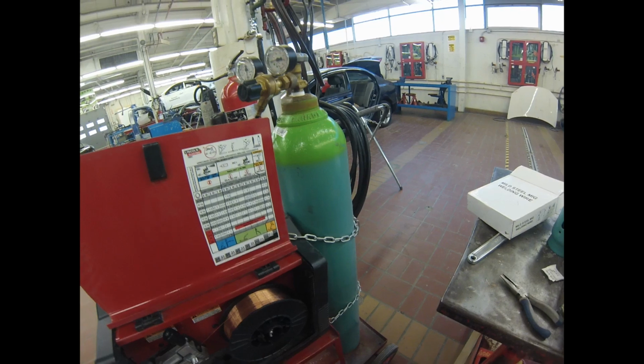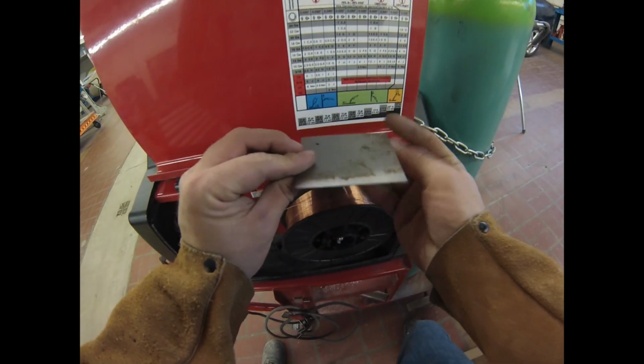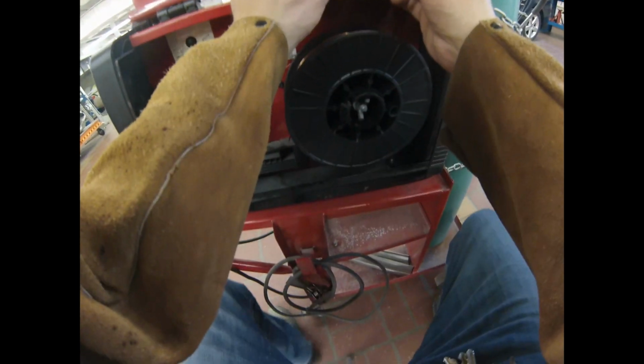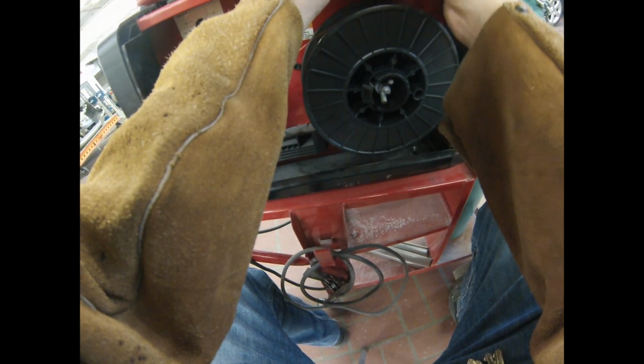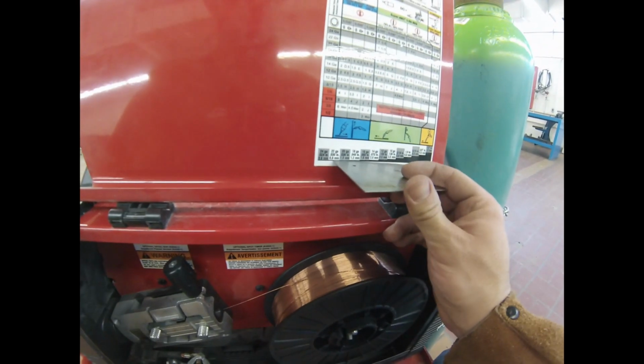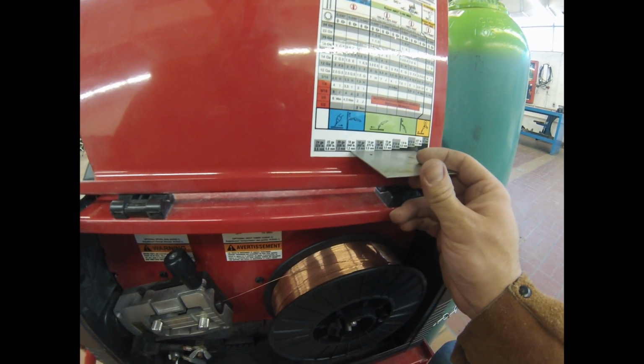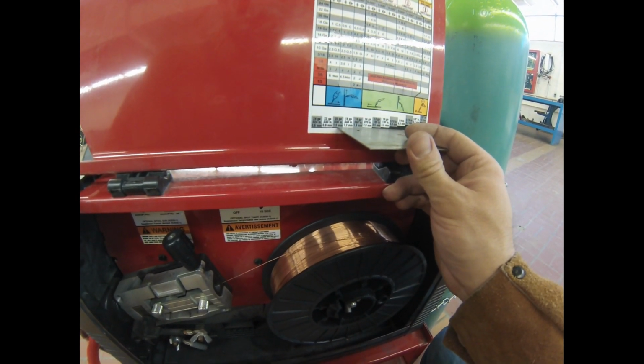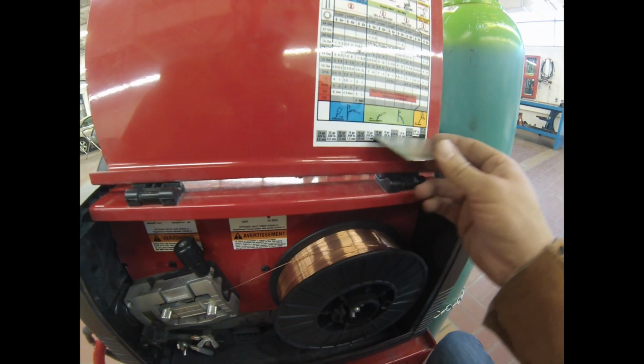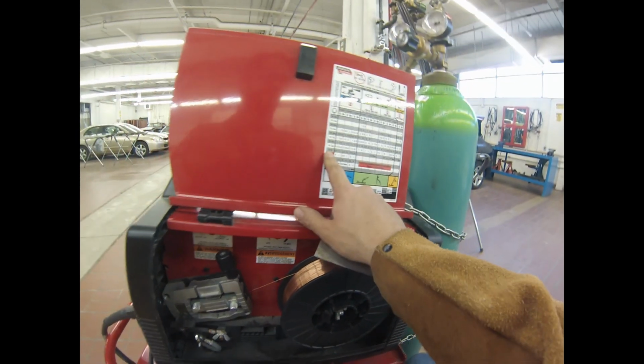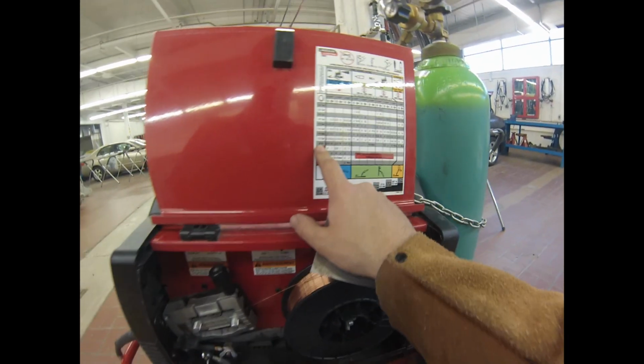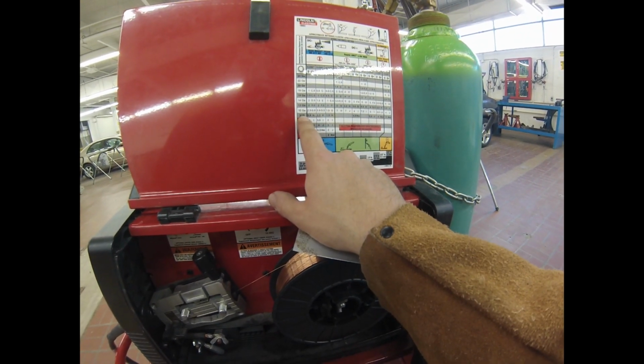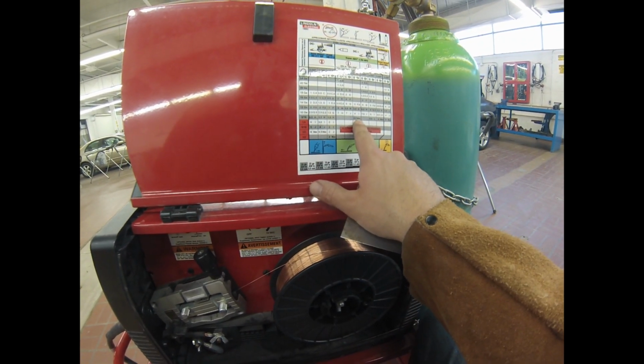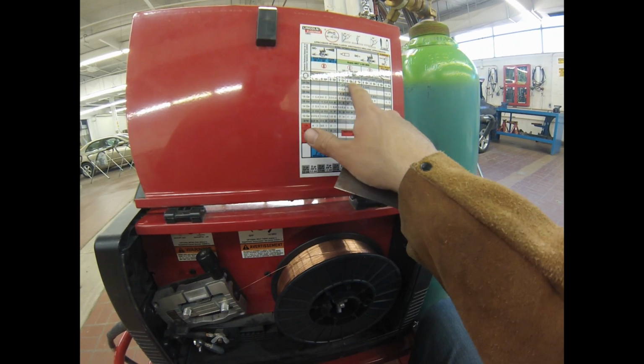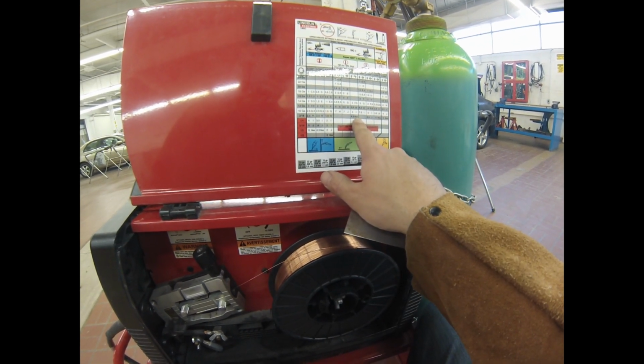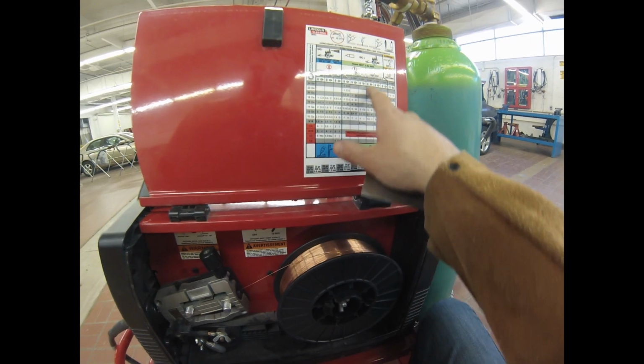If you're wondering what kind of metal you're actually welding, you can take a piece of metal and you can set it up at this thing and go, is it thicker than 22 gauge, 20, 18? And this one is 20 gauge steel, and you can see it's the same thickness. And this welder, even though it's just a small welder, but it's 220, this 180 welder will weld up to 3/16, right? So you set it to 4.5 for drive roller speed, and for the voltage, you just crank it right to the top, as far as the alphabet will go.